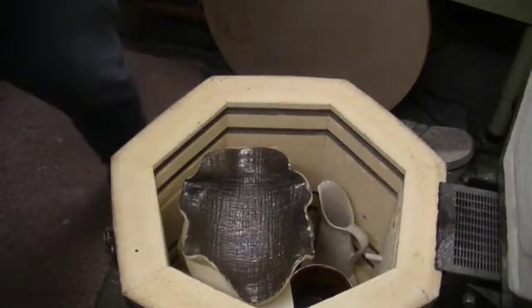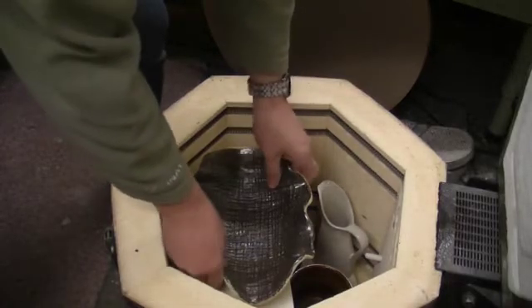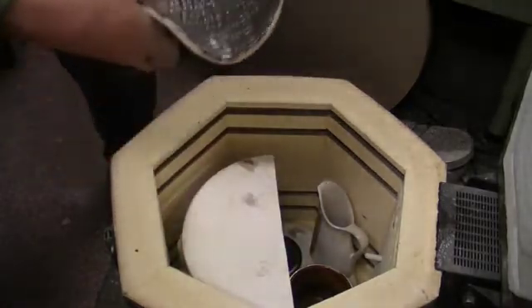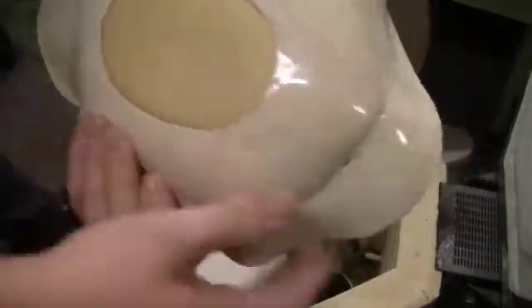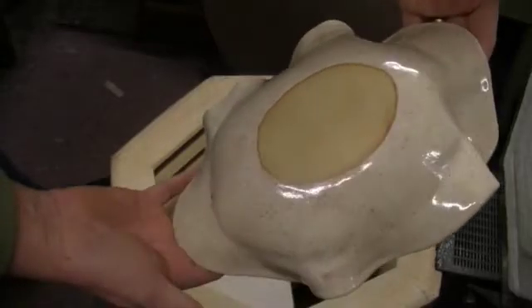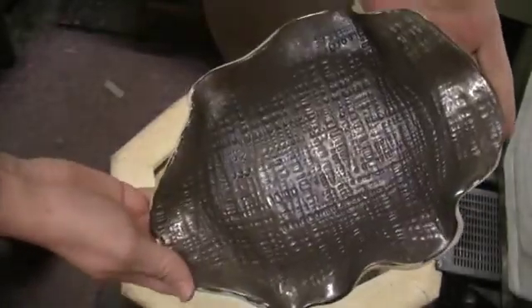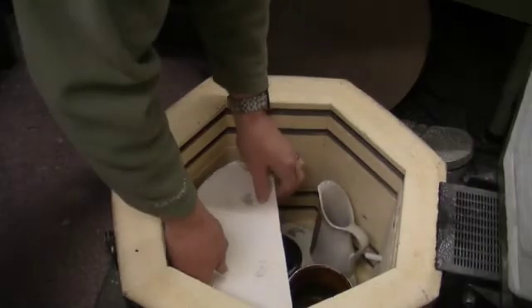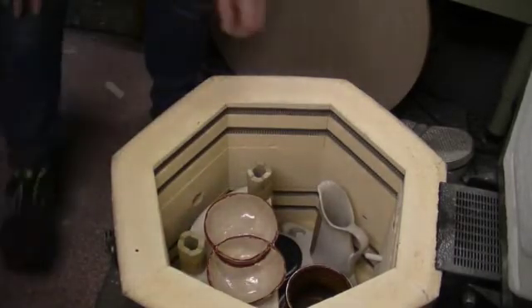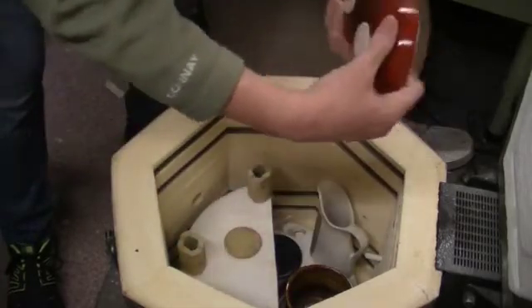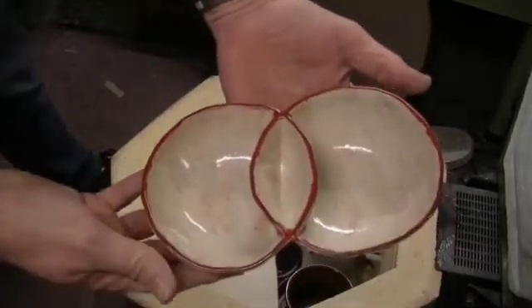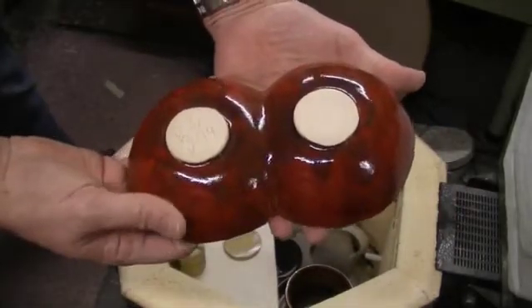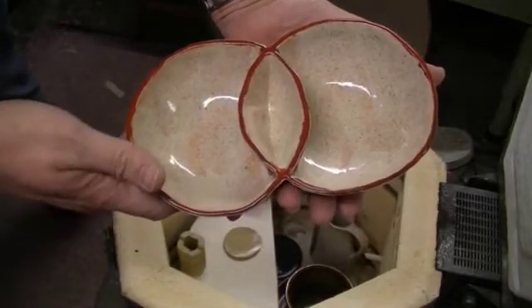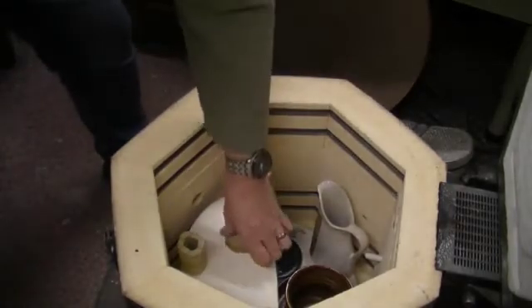Oh, that's nice, metallic glaze. Still a wee bit warm, it's 50 degrees, but there you go. So that's come out very nice. A nice metallic-y colour. Lovely, that's that one. These shells out of the way, which are a bit warm still. So we have this one, which has come out nice, and a nice red. Looks a bit odd, but there you go. So that's that one, good fire in there. The cones are right at the bottom, so we'll get to them shortly.